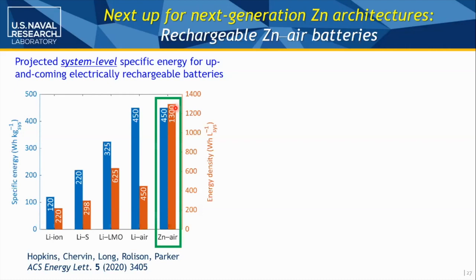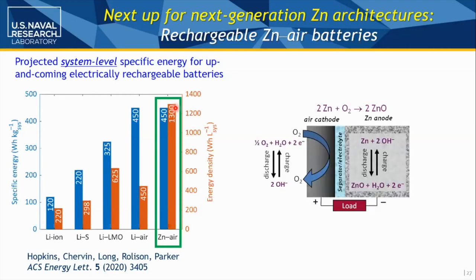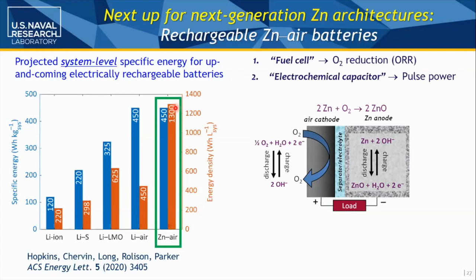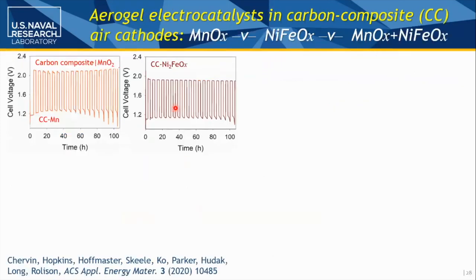And the fun thing about zinc air is you've got to do 4 electrochemical devices well. You've got to have the ability to reduce oxygen in an alkaline electrolyte, so it's like a fuel cell. You need pulse power, which typically air-breathing cathodes don't give you, but we've got ways to get around that with architected designs. You have to have the zinc not make dendrites, solve that problem. And then at the end of the day, you have to evolve oxygen, so you have to have alkaline electrolyzer function. All of that's got to work in one nominal two-terminal system. So we've come back to aerogels.